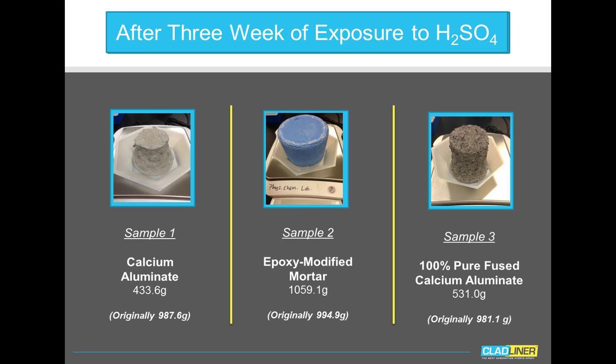After 3 weeks of exposure, as I mentioned, we did this weekly, but we started seeing material differences after 3 weeks, so we included the results of week 3 in this presentation. Sample 1, the calcium aluminate, after 3 weeks, was down to 433 grams. Remember, we started at 987. That's about a 56% drop already in the weight. The epoxy modified mortar was just over 1,000 grams. And the pure fused calcium aluminate was down at 531 grams.